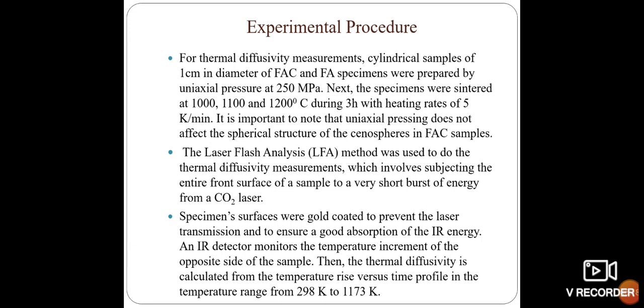The laser flash analysis method was used to do the thermal diffusivity measurements, which involves subjecting the entire front surface of the sample to a very short burst of energy from a carbon dioxide laser. The specimen's surfaces were gold coated to prevent the laser transmission and to ensure a good absorption of the IR energy. An IR detector monitors the temperature increment of the opposite side of the sample. Then the thermal diffusivity is calculated from the temperature rise versus time profile in the temperature range from 298 Kelvin to 1173 Kelvin.